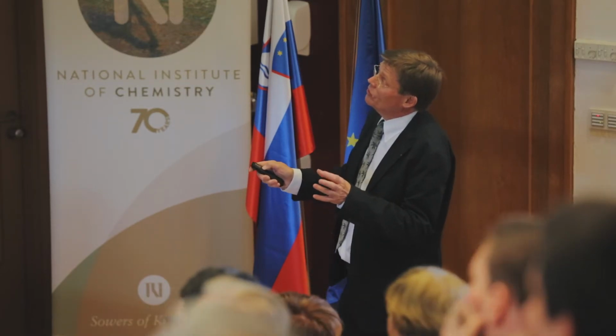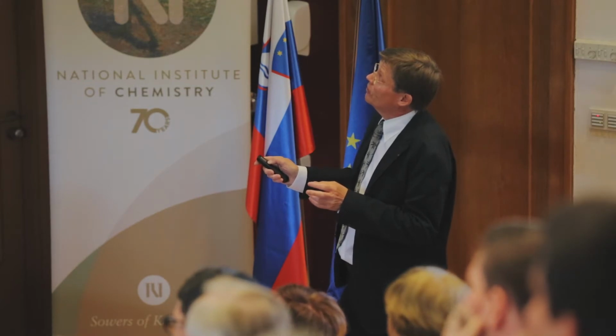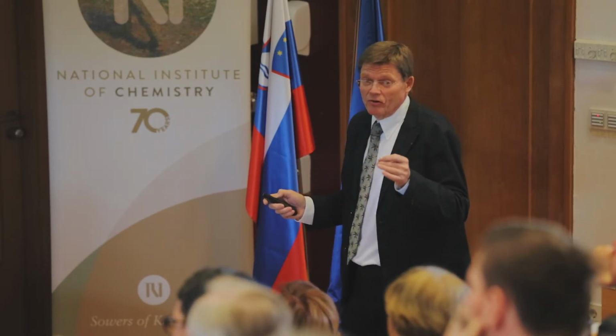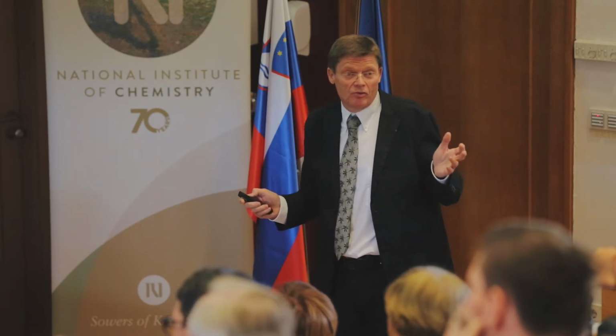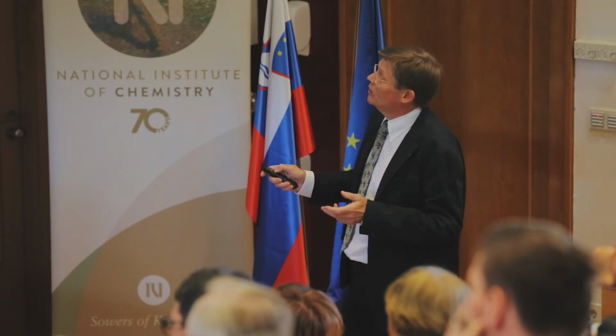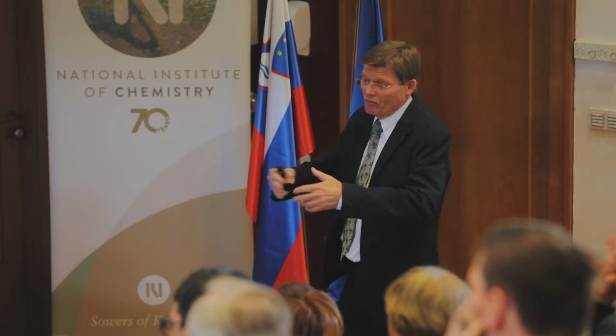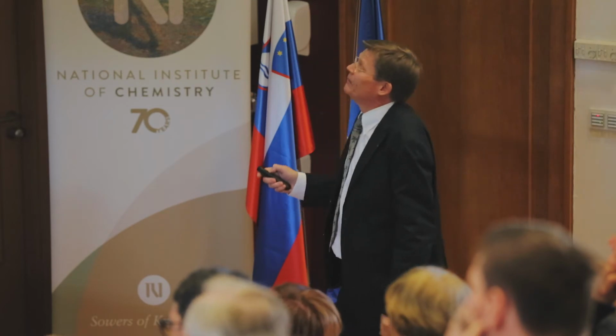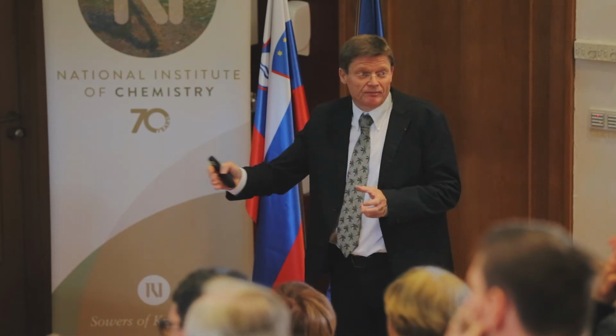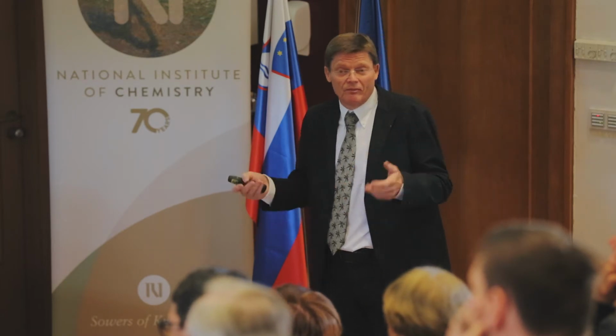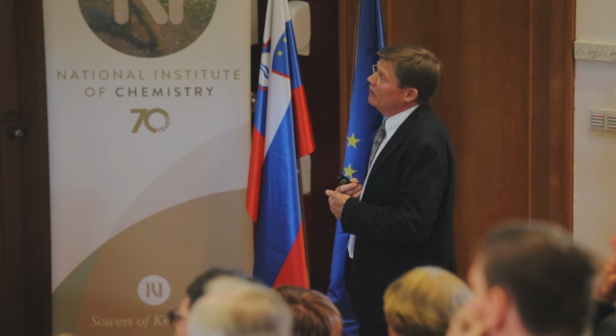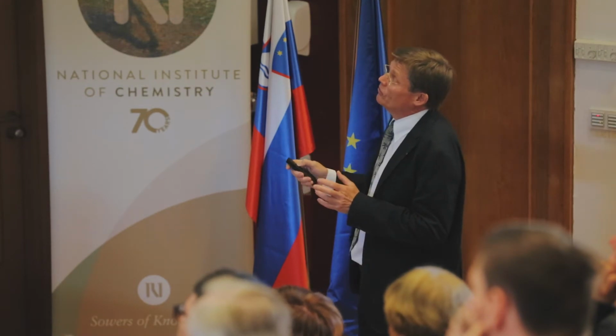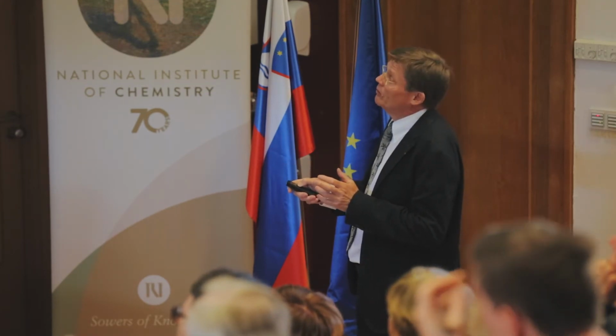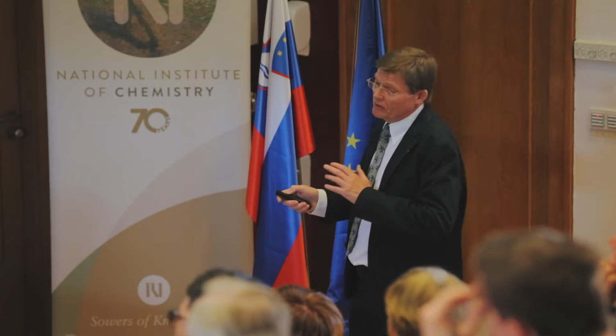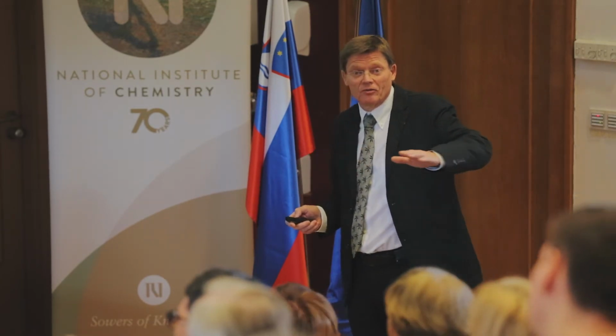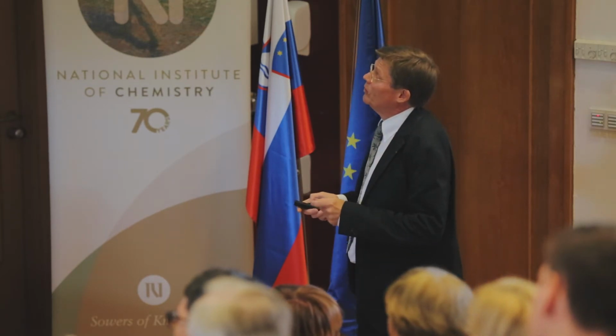Anyway, when you just concentrate on the diffusion aspect, the diffusion coefficient of this composite for silver is the highest chemical diffusion ever seen at room temperature. It's orders of magnitude higher than in lithium cobalt oxide, for example, which determines the rate at which lithium is dissipated. It's even higher than sodium chloride in liquid water. It's very, very high, but understandably high. I think we are on the right way of making what we call artificial mixed conductors, namely having alternating layers of good ion and good electron conductors, with thin film techniques, for example. I hope we will succeed in this.